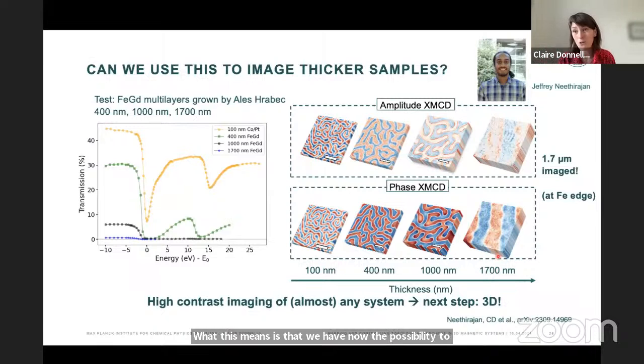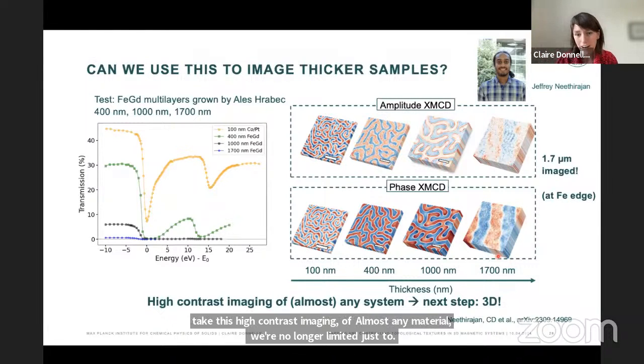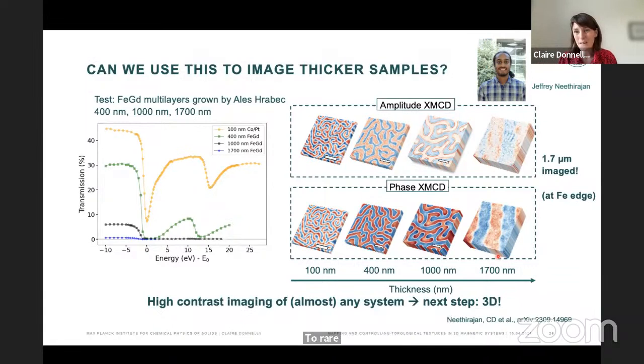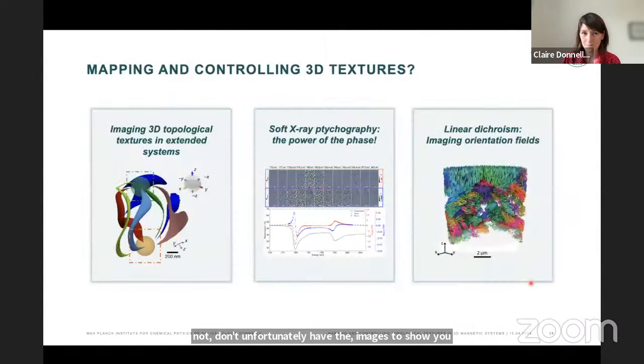What this means is that we now have the possibility to take this high contrast imaging to almost any material. We're no longer limited just to rare earths, and can then image the 2-dimensional projections, which are the basic ingredient for 3D magnetic imaging. So hopefully the next step is going to be 3D. Unfortunately I don't have the images to show you now, but this is something I hope I'll be able to show you in the next few years.